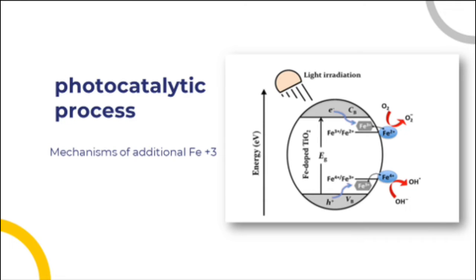The first step consists of the formation of Fe²⁺ ions, which results from the transfer of photogenerated electrons from titanium dioxide to Fe³⁺ ions. Fe²⁺ ions are relatively unstable compared to Fe³⁺ ions because they do not have a half-filled orbital. The trapped charge can be released from Fe²⁺ ions and afterward migrate to the semiconductor surface to initiate the photocatalytic reactions. In this sense, Fe²⁺ ions can be oxidized to Fe³⁺ ions by transferring electrons to molecular oxygen, which is adsorbed on the surface of titanium dioxide to form superoxide anion, which is a highly reactive oxygen species.